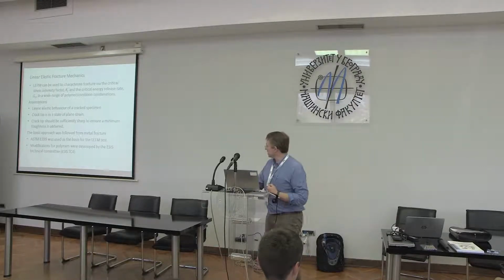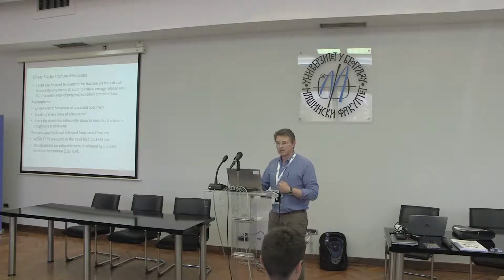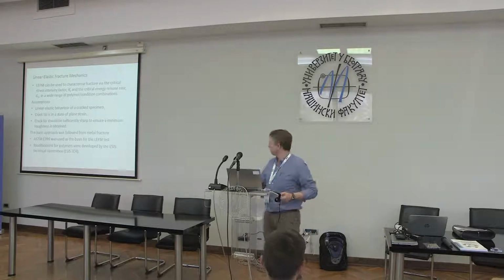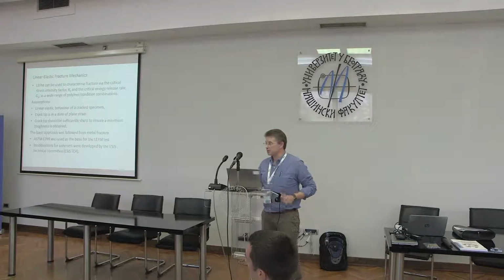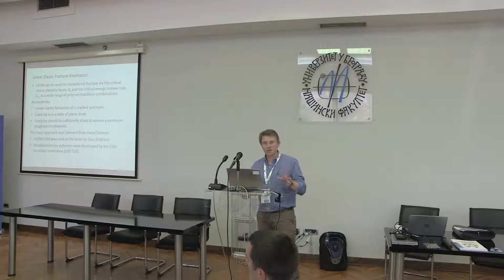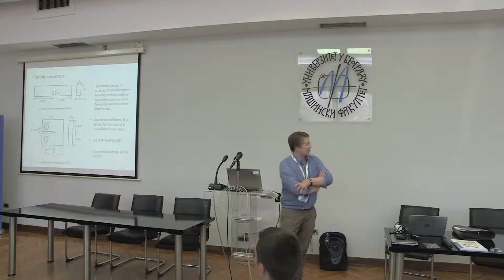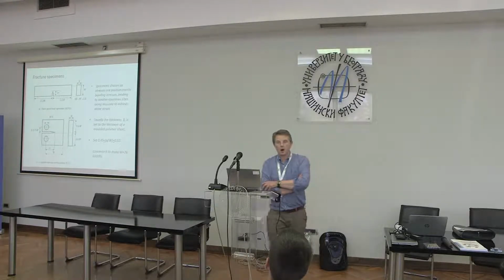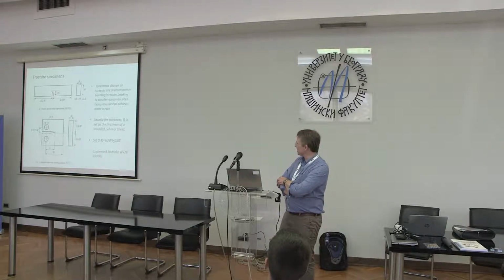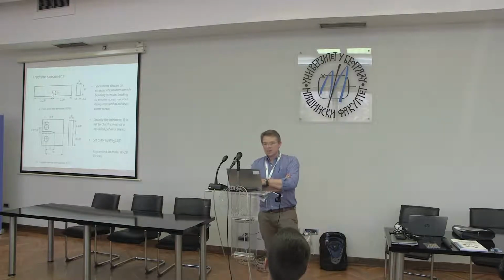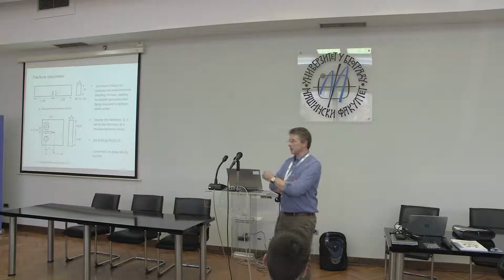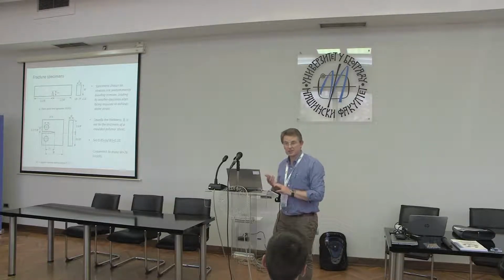So in basic, we're starting off with the metals method, which was ASTM E399. So those of you more metals-based will be familiar with that. And that was used as the basis for the polymer fracture test. And of course, then the idea was to modify that based upon what we know about polymeric materials. So the fracture specimens are relatively familiar. We use a single edge notched bend specimen or a compact tension specimen. So we favour these specimens because the stresses are essentially bending stresses, so we can satisfy our plane strain conditions for minimum size requirements.